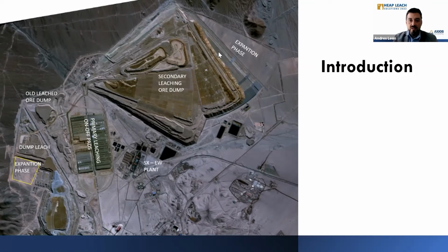So for instance, for this area, two different types of overliner materials were developed. As you can see, the gray areas represent areas with a very well selected and processed material, mainly for drainage, and the other areas are a different type of material with less processing, focused only on protection of the liner system. This is to optimize and reduce the amount of material that needs to be processed to get very good drainage in general. Same here in this case.